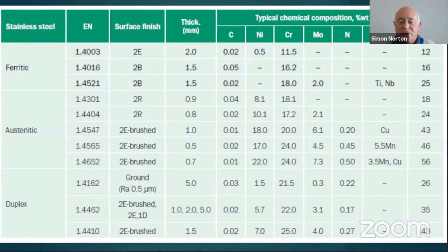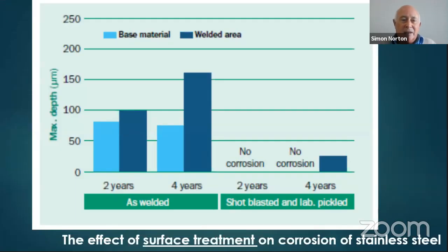This was used for an experiment, which I'm just going to show you some results of, to emphasize the importance of surface finish. These coupons were exposed in the atmosphere for 2 and then 4 years, and then the as-welded and prepared surfaces were evaluated. So the base material is shown in the light blue and the welded area in the dark blue. And you can see that the maximum depth in microns in 2 years and 4 years has obviously slightly increased, but when they did shot blasting and lab pickling, there was no corrosion. So treating the surface has a huge effect. So in your design, you need to decide how you're going to treat the surface of your stainless steel.